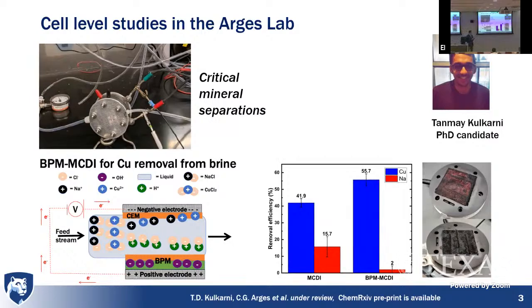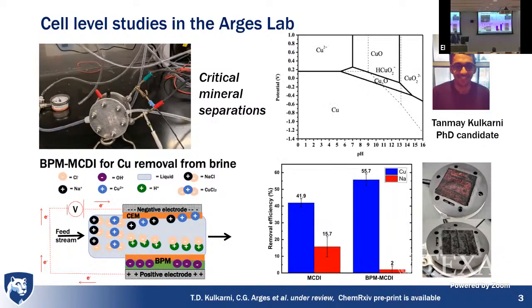And so my student, Tanmay Kulkarni, who's a PhD candidate with my group, this is work that he's doing. And you can see here, he's pulled out copper at a much greater rate than sodium. And then by creating this acid environment in the bipolar membrane, when we plate the copper, we get its metallic form and not a metal oxide. That metal oxide can be problematic because it can passivate the electrode. When you get the metal oxide, you get this bluish color copper oxide, but when you get the metallic copper, you get the copper that we know in copper wiring and copper piping. And this is informed by Pourbaix diagram principles, right? The thermodynamics, the electrode potential and pH that we can exploit to achieve selective separations.